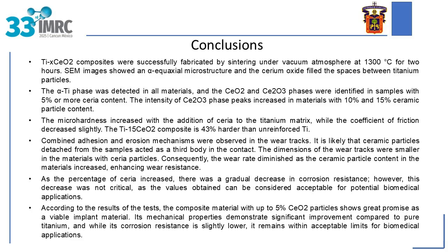What can be concluded based on the results? Titanium ceria composites were successfully fabricated by sintering under vacuum atmosphere at 1300 degrees Celsius for 2 hours. SEM images show an alpha equiaxial microstructure, and the cerium oxide filled the spaces between titanium particles. The alpha titanium phase was detected in all materials, and the cerium 4 oxide and cerium 3 oxide phases were identified in samples with 5% or more ceria content.